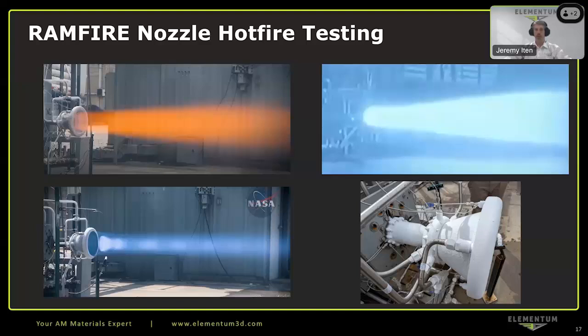Basically, you're flowing the cryogenic fuel and oxygen through the part to keep the part cool. You get some preheat to the fuel as well before you combust it. And that's how you can make a rocket engine nozzle out of aluminum without melting it. And it also is really why additive manufacturing is so beneficial for these regeneratively cooled rocket engines, because it's very difficult to make through traditional processing because you're using conformal cooling channels throughout the part.